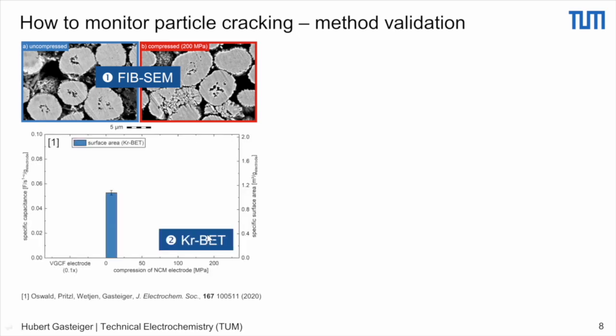So what we try to do here is to develop a method based on BET, but using krypton instead of nitrogen for the BET measurements, as krypton is about 2 orders of magnitude more sensitive. Now, when you measure powders, that of course is irrelevant. You can just use enough powder to conduct a nitrogen BET, but when you use electrodes, then of course your surface area, your total mass, is too little. And so in our case, it only works really when we use krypton BET.